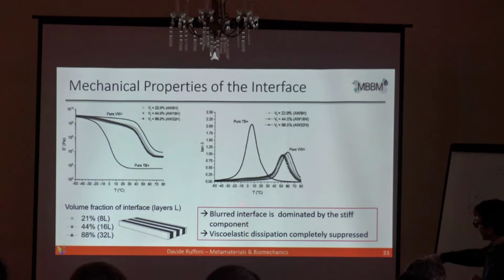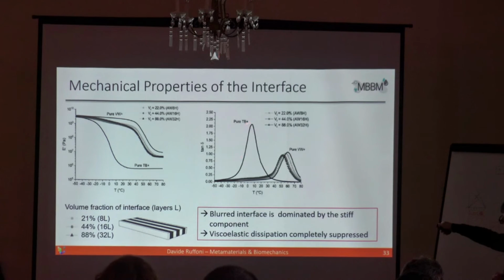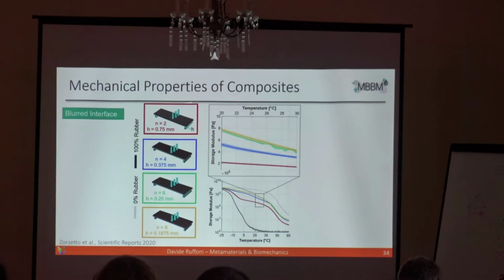So, in other words, we say that the interface, which forms when you're mixing the two voxels, is dominated by the stiff component, and actually the viscoelastic dissipation is completely suppressed. As you can see here, the soft component shows this viscoelastic dissipation, the peak in tan delta at 0 degrees, which is completely suppressed when you mix it with the stiff component. So this was already one of the two main findings so far.